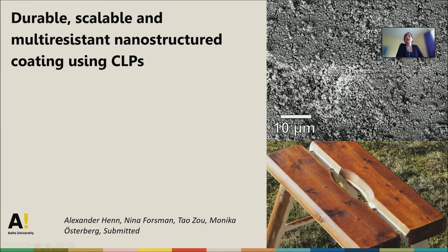This is a scanning electron microscope image of the coating. You can see the small spherical particles here. And this is a stool that has been coated with this particulate coating. What you can see is that this brown color is quite useful if we think about wood coating, for outdoor furniture or your terraces, where you usually want to have this kind of color. I also use this picture to show that this is not only research done at nanoscale in the lab, but we can actually produce this coating on a bit larger scale. Now we are trying to commercialize this and also see how it works in real life.